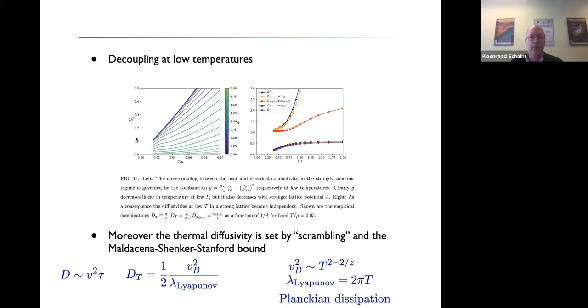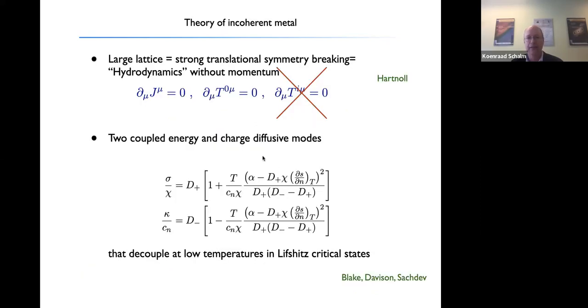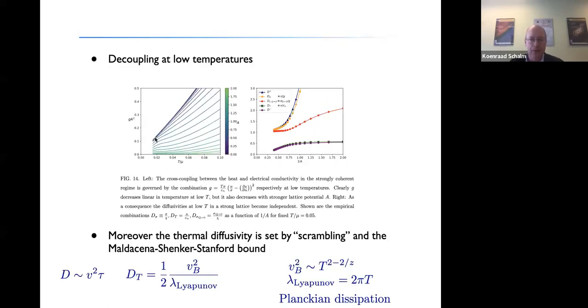Here you see the cross-coupling. This is the effective cross-coupling. It's not written here, but this is the effective cross-coupling between the charge flow and the heat flow in these systems as a function of temperature and as a function of the lattice strength A. And as you increase the lattice strength A, you see that this cross-coupling goes down a lot. And also as you decrease the temperature T, you also see that this cross-coupling goes down a lot. So at very large A and very low T, there are essentially 2 independent transport sectors. And here you can see this as well.